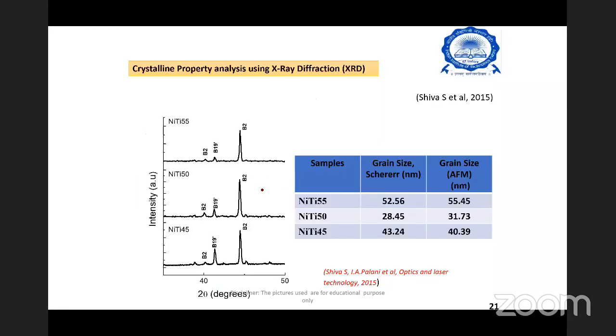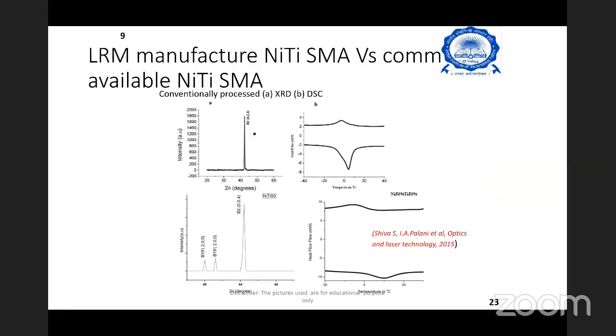The most important thing is, we were concerned about the material behavior, basically the structural characteristics of it, because structural characteristics will give me an indication at which point exactly my SMA effect happens. Basically, this is the B2 phase. This B2 phase will be helpful for me to investigate how the SMA effect happens. I could observe a B2 phase with these additive manufactured shape memory structures, which would be helpful for me to proceed further. And in fact, we compared the results with the conventionally available NiTi shape memory structures, which is available in the market.